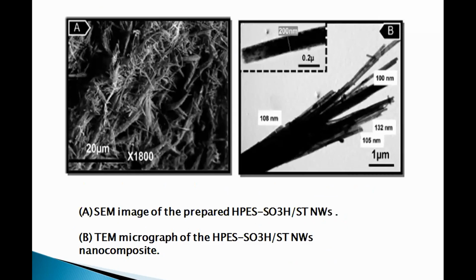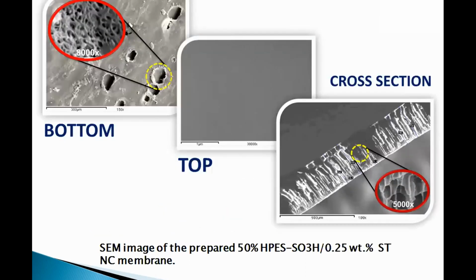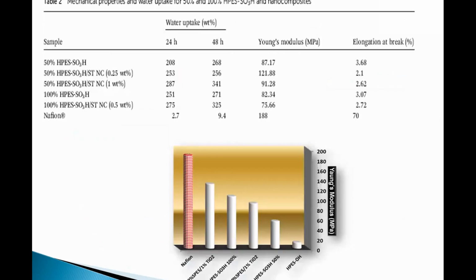This is the same images for the composite membrane of polyether sulfone with the sodium titanate. As we can see, the sodium titanate is covered with the polyether sulfone. And this is another image for the membrane. And we have measured the mechanical properties and water uptake for the membrane for the 50% and 100%.